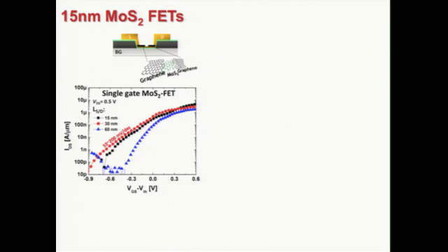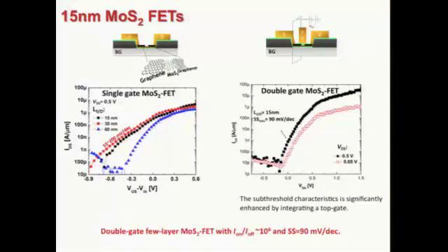But 15 nanometer is the minimum that we have right now. So all of them show very low off current, as expected. It's a wide bandgap semiconductor and very linear subthreshold characteristic. But as you see, the 15 and 30 nanometer channel are already affected by the short channel effect. So it's less steep. The swing has increased. So that's we need to improve it by applying the top gate.